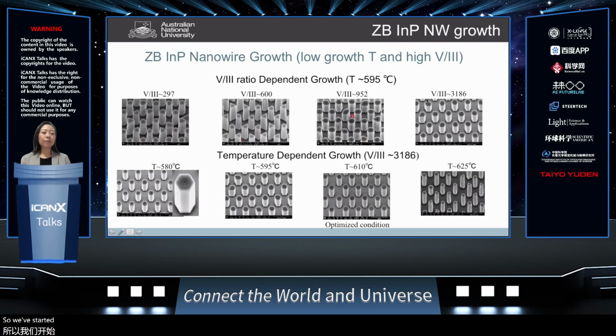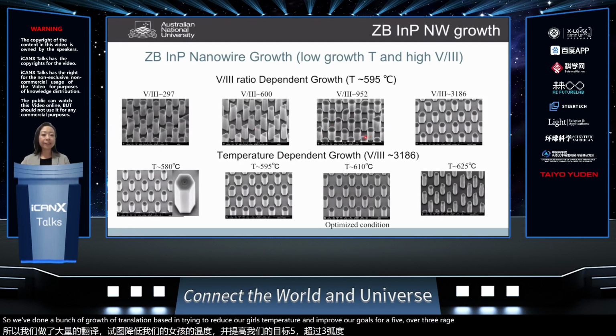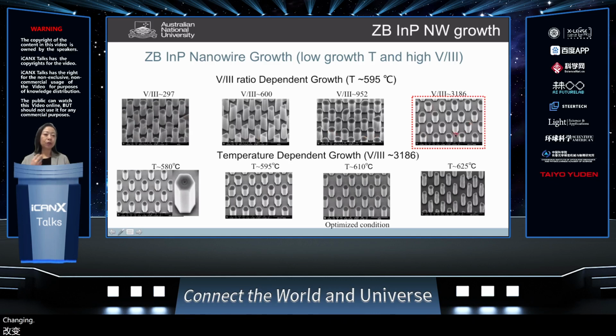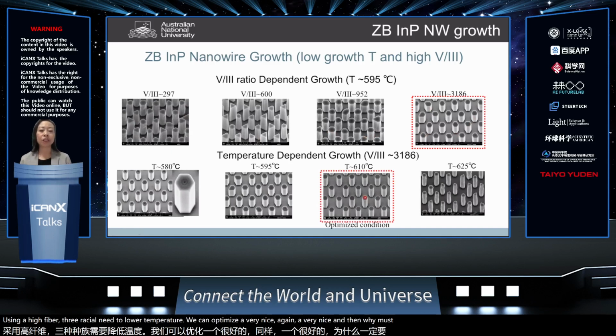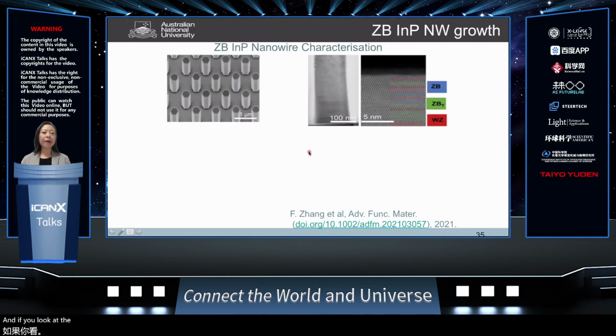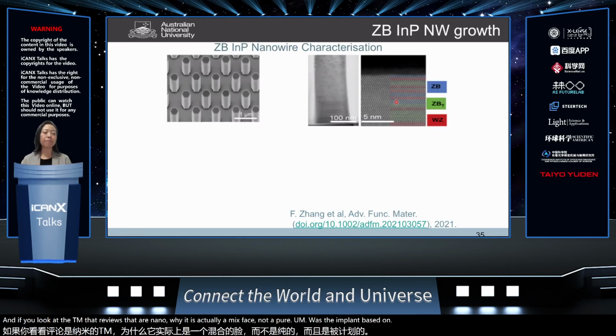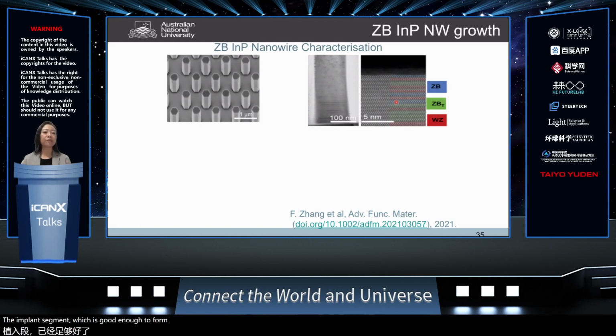So we've done a bunch of growth optimization, basically trying to reduce our growth temperature and improve our growth rate. And indeed, you can see that by using a high V/III ratio and lower temperature, we can optimize a very nice nanowire morphology. And if you look at the TEM, it reveals that our nanowire is actually a mixed phase, not a pure zinc blende phase. We have a lot of zinc blende segment, which is good enough to form the base for nanowire quantum well growth.